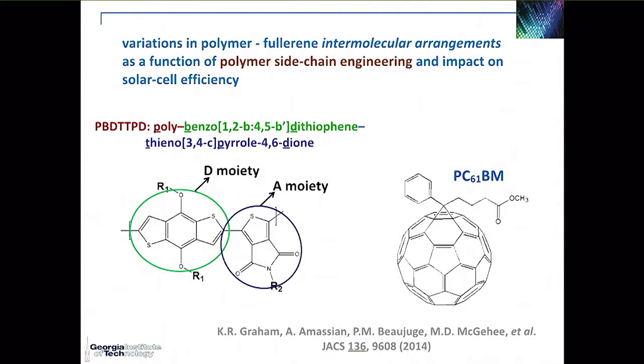Pierre Beaujuge synthesized a number of those copolymers, which have along their backbone alternating electron-rich moieties, such as benzodithiophene, and electron-poor moieties, such as thienopyrrole diones, TPD. Now, in the jargon of organic solar cells, those electron-rich moieties are usually referred to as a donor moiety, and the electron-poor as an acceptor moiety, which is a bit confusing in the sense that the copolymer itself, in the charge separation process, the whole copolymer chain acts as an electron donor. But in the rest of the presentation, I'll refer to the donor moiety as that benzodithiophene, the acceptor moiety as that thienopyrrole dione.